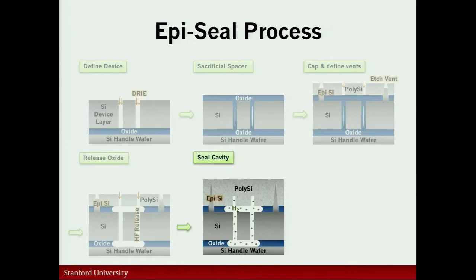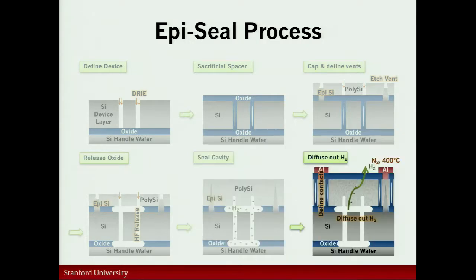And then we go right back into the Epi reactor pretty much as quickly as we can and grow up another 10 to 20 microns of polysilicon that seals up the vents that we used for releasing the MEMS device and seals everything so that what's trapped inside is just leftover hydrogen gas and otherwise a sealed micromechanical element buried inside the wafer. We do some last steps that help us establish the electrical contacts from the surface down to the MEMS layer. We can heat the wafer in a nitrogen furnace, and that drives out the residual hydrogen, so we can reduce the pressure that's trapped within the resonator, get down to pressures that will give us higher Q.